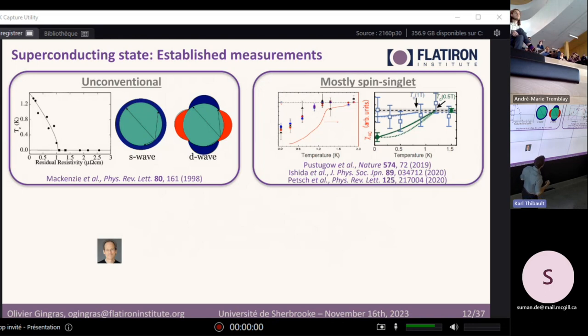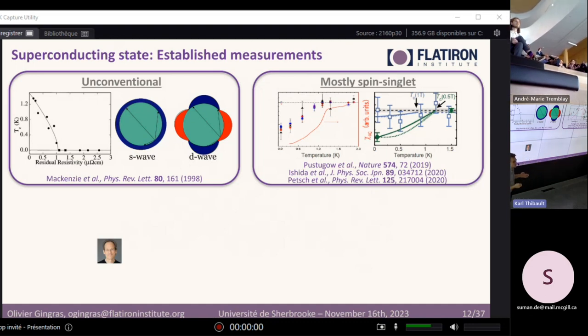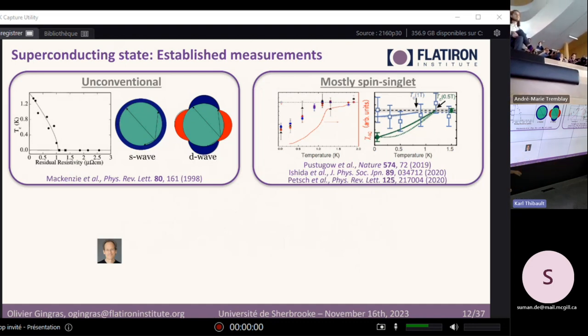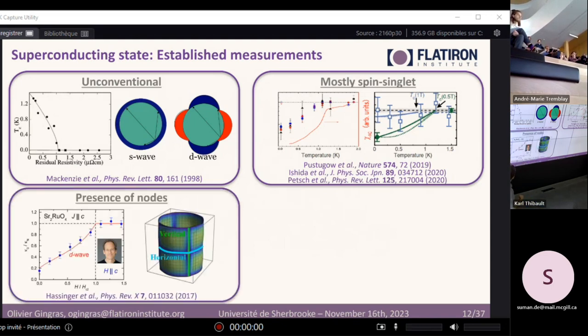And for a long time, they were heating up the sample by doing this measurement. So they thought it was the signature of triplet, but by carefully redoing this experiment just a few years ago, they highlighted the totally opposite behavior.